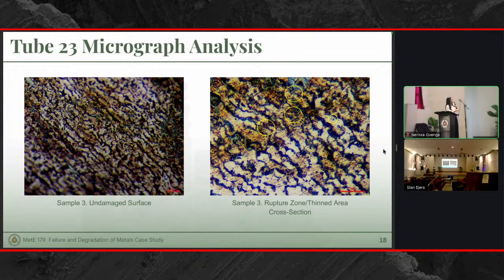However, for the ruptured zone or thinned area, there is some degradation of the pearlite structure and also some formation of spheroidization, which is evidence of overheating. So overheating could change the microstructure of the tubes, and so possibly the other failure mechanism of tube 23 is overheating from steam impingement coming from tube 22.